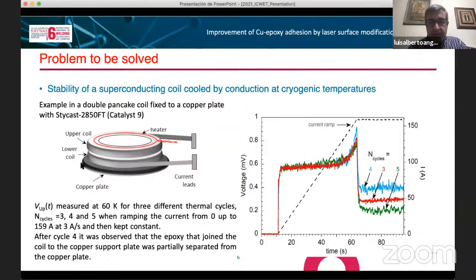The coil is fixed to a copper plate, and this is fixed to the cryo cooler. And usually we use Stycast 2850FT to fix the coil to the copper plate. In principle, we were working with aluminum. The catalyst 9 produced a good effect, but when we were working with copper, we started to see some problems.